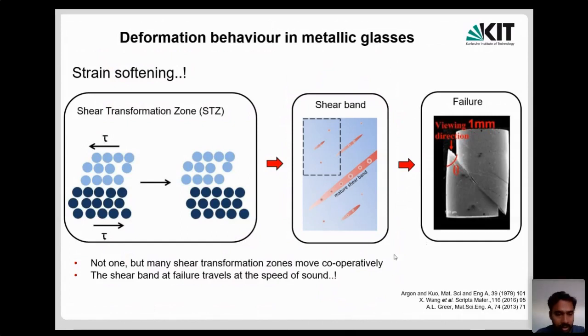This is just a sort of summary slide for you to understand how the deformation is proceeding. So you have a shear transformation zone, which is happening here, in different sheared regions in the material. And these sheared regions, each ball is again a shear transformation zone, and they all coalesce or cooperatively move to form a mature shear band. And once you form a band, they immediately break, and you get such kind of failure very quickly. And during the breaking of this band, they actually break at a very high velocity. They almost travel at the velocity of sound.